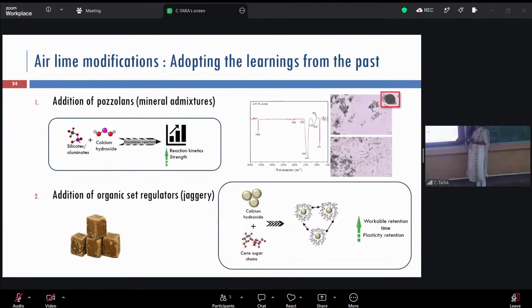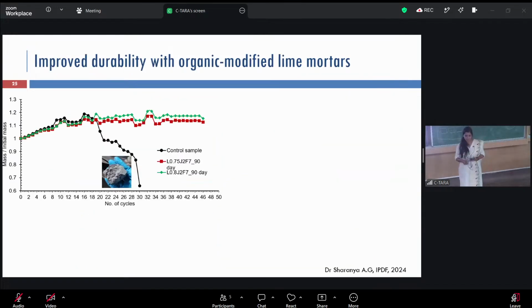And then we optimized the dosages. So this is a thin section microscopic image from a freshly mixed lime. And you can see that jaggery getting attached over calcium hydroxide molecules. And then we evaluated it in much more depth using Raman and other spectroscopic measures also.